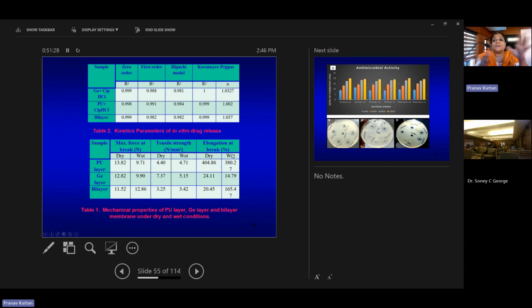That is, a sustained release of ciprofloxacin is found, and it also satisfies the Korsmeyer-Peppas model of drug release. That is, it has an n value of greater than 1. That is the last column. It shows that this drug release is non-Fickian. Non-Fickian drug release means that it not only depends on the amount of drug, it also depends on the kind of matrix from where the drug is releasing. So that kind of release kinetics this ciprofloxacin is showing.